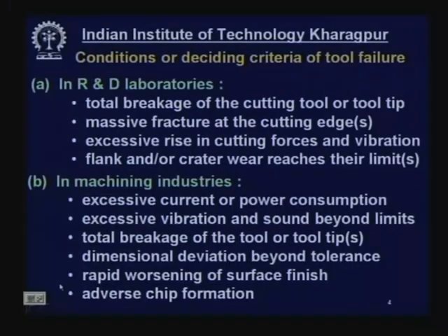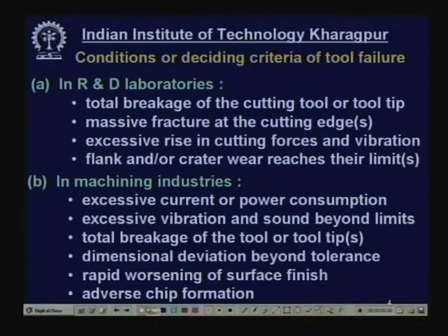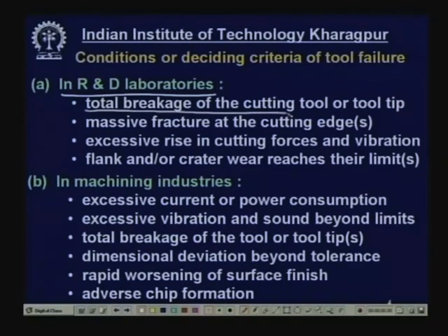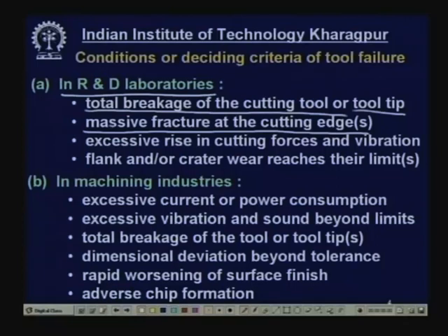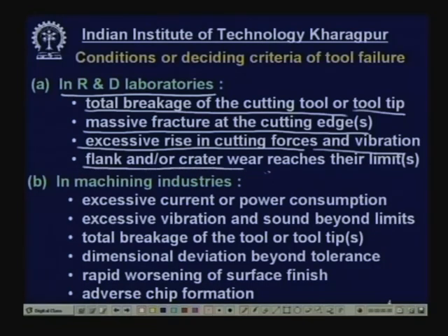In R&D laboratories, failure is understood when the tool breaks totally — total breakage of the cutting tool or tool tip. Massive fracture at the cutting edges, where chunks of material come out, also indicates failure. Excessive rise in cutting forces with a lot of vibration indicates the tool has failed and machining must be discontinued. Most importantly, when flank wear and crater wear reach preset limits, the tool is considered to have failed and must be withdrawn.